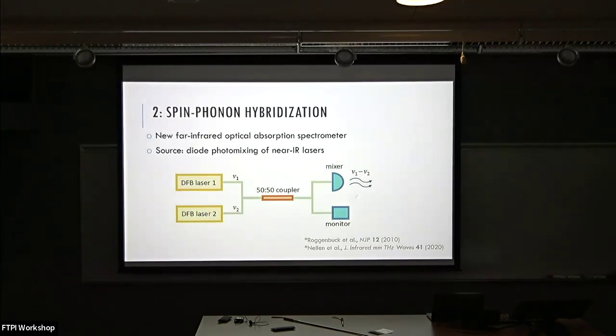So what we try to do is a slightly different method where we measure the absorption directly through the temperature of the sample. This has been done before, quite long ago. But yeah, here, again, it's kind of a revival. I think it works very nicely for this. And the second nice thing is the source. So it's not easy to get frequencies in this range, especially if you want to do a wide temperature, a wide frequency range. So what we found is this very nice thing where you have a diode, so-called mixer.